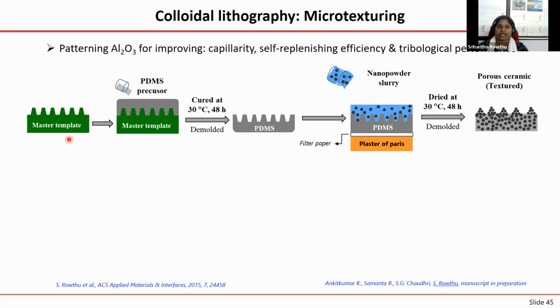Once you have this template, you can pour your PDMS. PDMS is polydimethylsiloxane. It is nothing but like your phone cover, that is a silicone material. You pour it on this and let it dry, which is actually called the curing process. There is a covalent bond formation that happens, and once you demold the PDMS after curing, you're going to end up having the negative impression of your template on this PDMS.